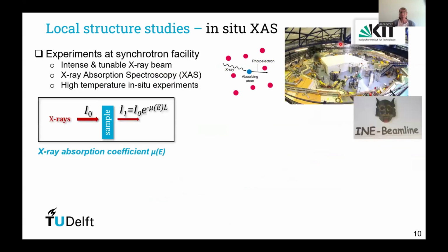How do we do that? We use experiments. We use X-ray absorption spectroscopy experiments, which are performed at a synchrotron facility, and that's because we need very intense and tunable X-ray beams. Since we also want to look at the molten salt, so a melt, we need to do high temperature in situ experiments.